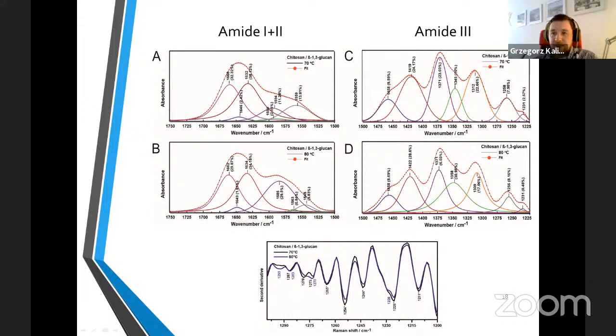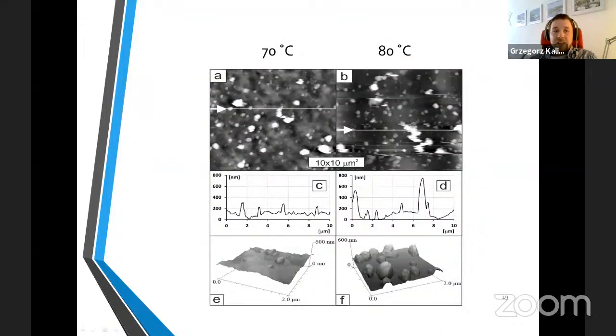Observations were also made in Raman spectroscopy, but FTIR brought more information. Raman spectroscopy indicates the same manner from amide range between 1200 and 1300, indicating change in secondary structure. And finally, atomic force microscopy. We investigated the surface to see that on the surface of our 80 sample, some bulky items were observed with different height comparing to 70 degrees. So 70 degrees sample has more smooth surface, and topology of 80 sample is more rough with these bulky items.